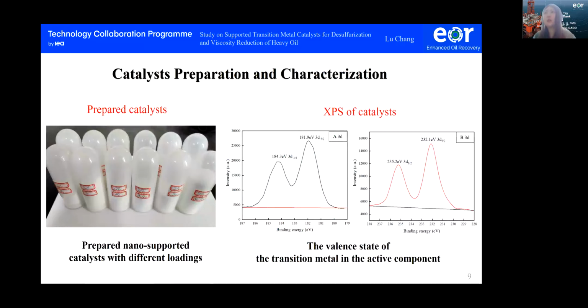And here comes the catalyst preparation and characterization part. Firstly, the nano-supported catalysts with different loadings were designed and prepared. Then we characterize them. We use XPS to detect the valence state of the transition metals and verify the loadings of the active components.